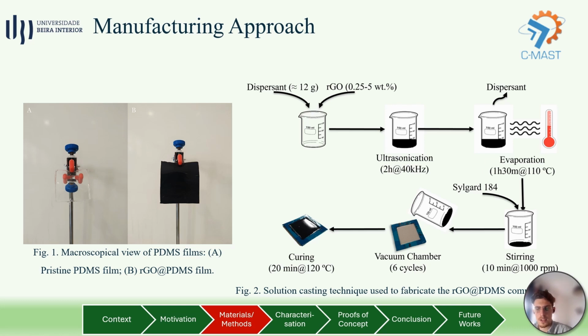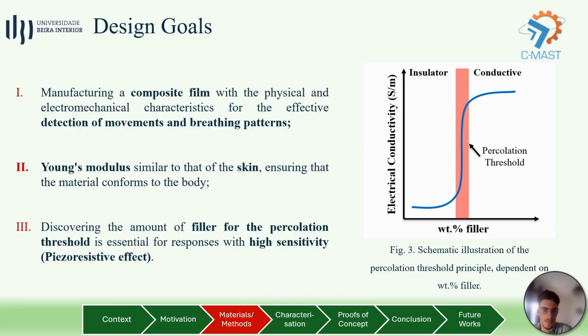At the end of this process, which may take up to 4.5 hours, we obtained a ready-to-use composite, which was very different from pure PDMS, as we can see from figure 1. Of all the produced samples, only the ones with an rGO content of 3, 4, and 5% showed us measurable electrical activity, and thus were the only ones used in the characterization techniques.